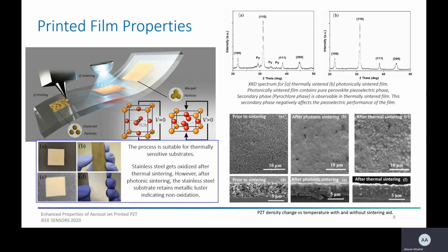In the case of thermal sintering, oxidation was evident as a loss of metallic luster and a resistivity increase, and that was not a problem with the photonic sintering, as obtained with the resistivity test. The extremely short processing duration prevents significant oxidation from occurring. An additional influence on the thermal sintering film properties is the high furnace sintering temperature and duration that leads to the release of lead oxide and the formation of pyrochlore phases, which results in weaker piezoelectric properties. The short pulse duration of the photonic sintering process prevents the formation of the pyrochlore phase and contributes to the improved properties.